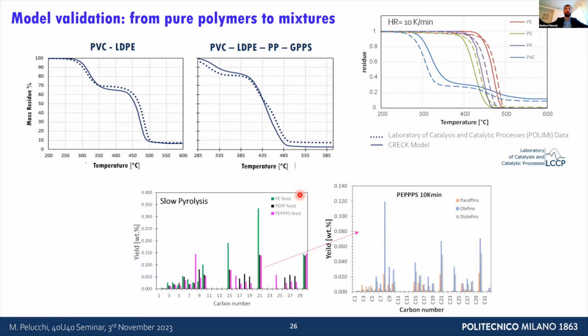We can make things more complex approaching the real plastic waste mixtures, and then we can look at binary, ternary, quaternary mixtures. You see the model by just summing up the single decomposition of each polymer. It works pretty nicely if you're considering only polyolefins, and so we can make a prediction of what the product distribution is.